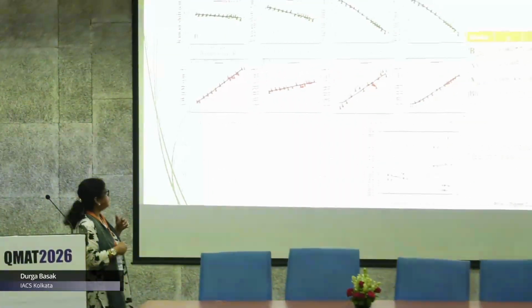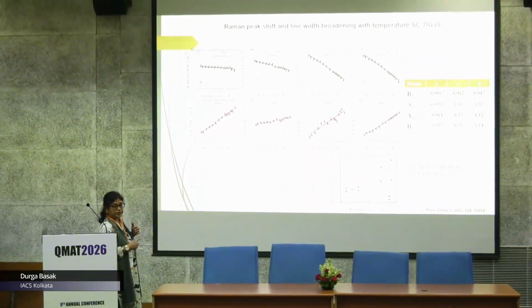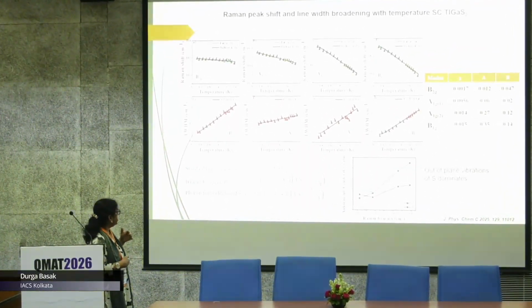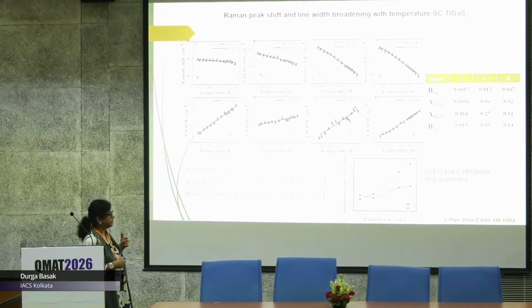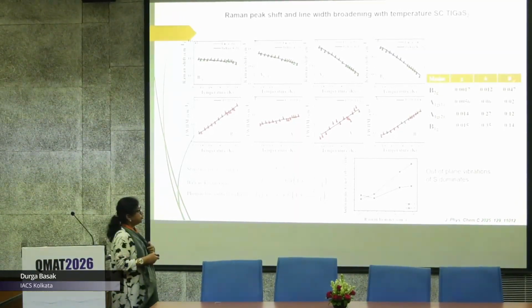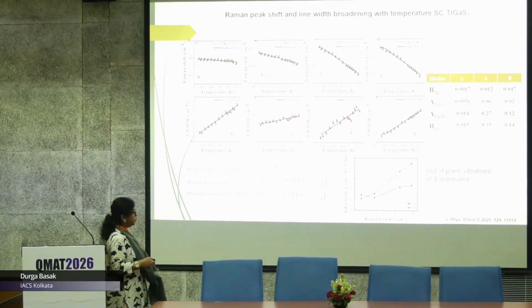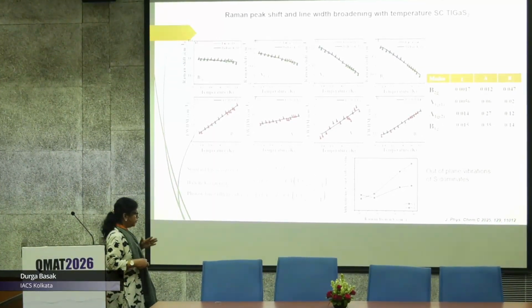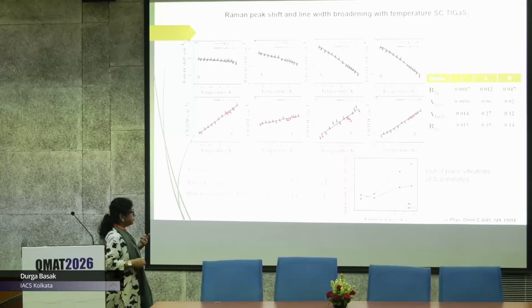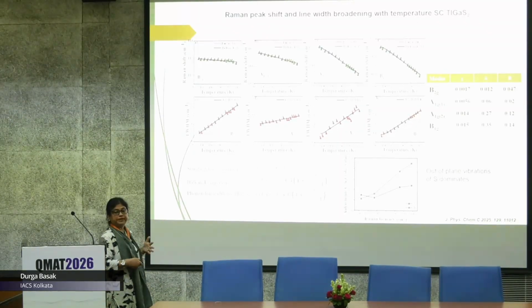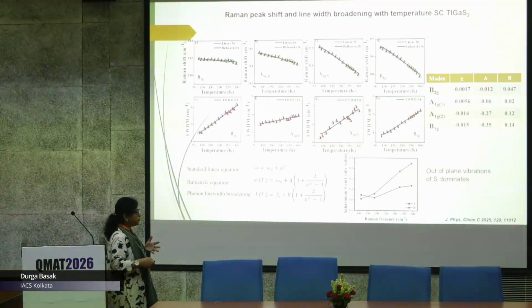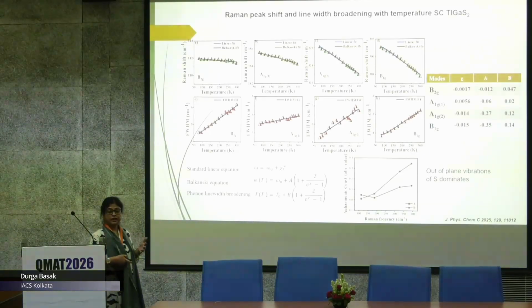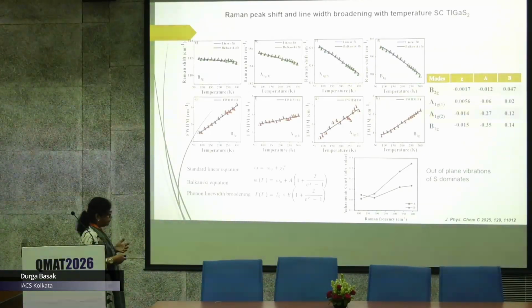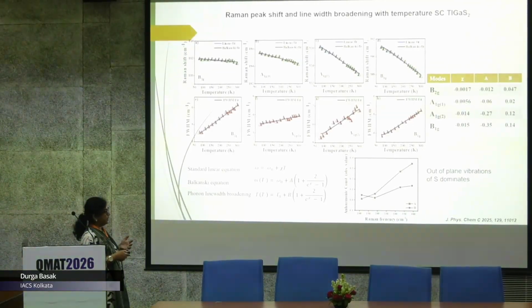And we see the phonon mode softening as we increase the temperature, meaning more interaction with the phonons as we increase the temperature. So we have calculated the value of B also, and as a function of Raman frequency, the anharmonic constants for the higher frequency peaks are quite high, and these are responsible for out of plane vibration of sulfur in that material. So this was all about single crystal thallium gallium sulfide.